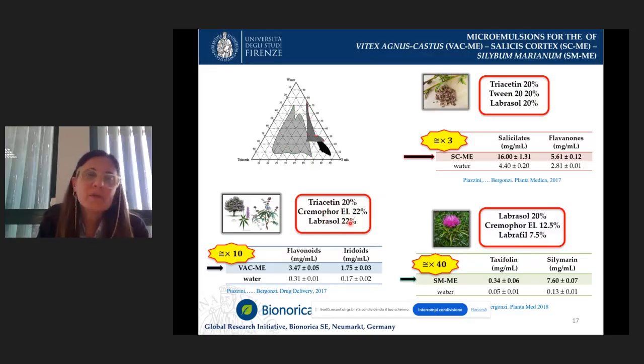The constituents are tensides and also solubilizing agents, and some of the compounds selected in the formulation are also penetration enhancers, which can improve the penetration and absorption across the intestinal barrier. Considering the solubility, with the optimized microemulsions we have good results in improving the solubility of the extracts. We have an improved solubility of 10 times in the case of Agnus castus, 3 times for Salicis cortex, and 40 times for silymarin.